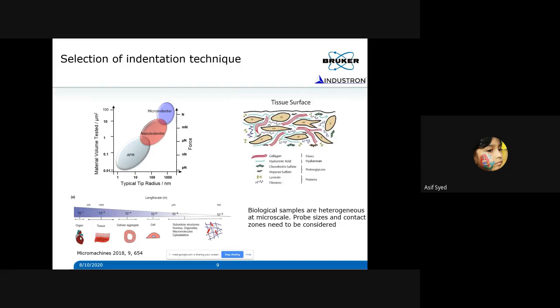For example, in Nanoindenter, you can have a micron size probe. At the same time, you can also have nanometer length, like a 30, 40 nanometer tip radius probe. So choosing the probe also depends upon which length scale you want to study. Do you want to study at the cellular level or tissue level or a much higher level? Okay, so that is what is important. So you have to correctly choose what type of instrument you want to use, and what is the shape and what is the size of the probe that you want to use, depending upon what you have as material.